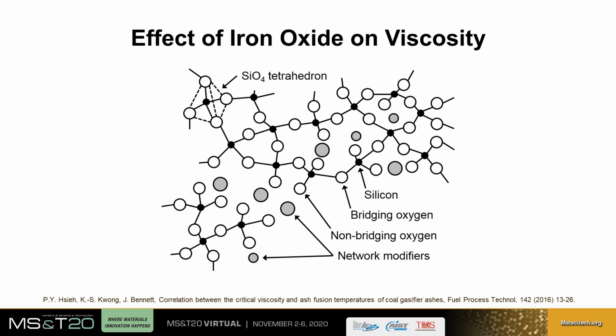Iron oxide exists in both a divalent and a trivalent state, while iron 2 oxide acts as a network modifier and reduces the viscosity of a silicate melt by increasing the number of non-bridging oxygens. Iron 3 oxide acts as a network former. Consequently, oxygen activity plays an important role in determining the effect of iron oxide on coal ash slag viscosity. However, that's not all that can be said about iron oxide.